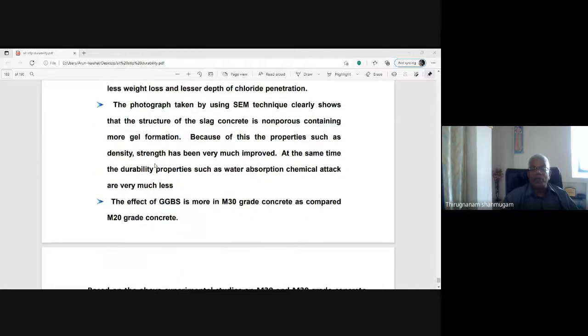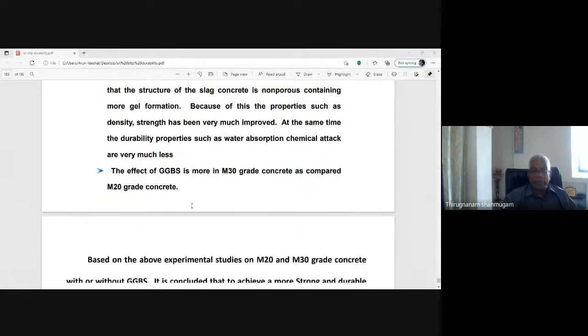The photograph taken by the SEM technique clearly shows that the structure of the slag concrete is non-porous, containing more gel formation. Because of this, properties such as density and strength have been very much improved. At the same time, the durability properties such as water absorption and chemical attack are very much less. The effect of GGBS is more in M30 grade concrete as compared to M20 concrete. So high grade concrete will exhibit more durable concrete.